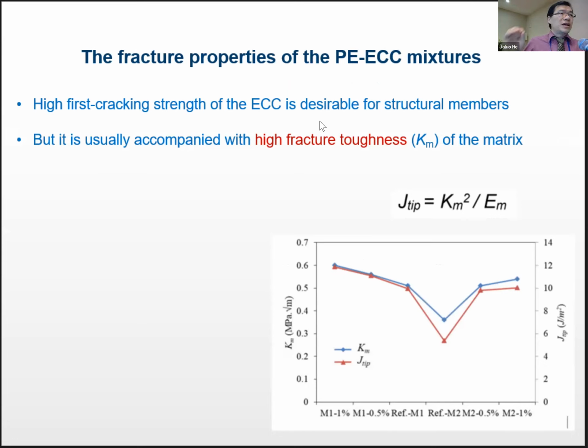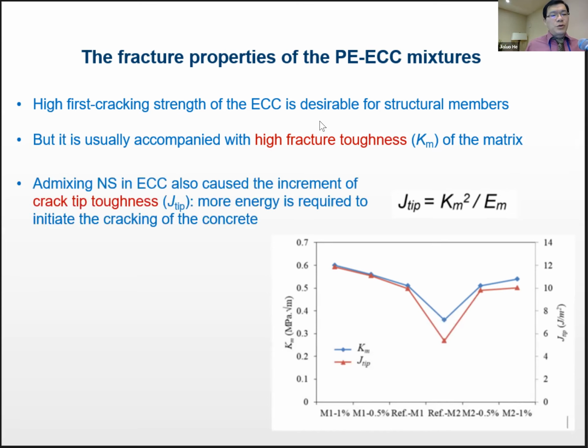When we look at, again, like I mentioned, the high first crack strength is desirable, but along with that, when you increase the first cracking strength, you're also increasing this so-called high fracture toughness, or the KM. And the KM is actually closely correlated with this crack tip toughness, or the J tip. And as I will show you later, in order to enable saturated micro cracking behavior, you don't want too high a J tip. So it's a balancing act. You don't want to make the matrix too strong. But because of nanosilica, you actually already made the matrix stronger.